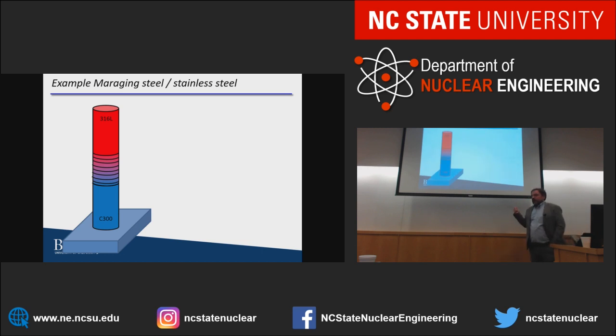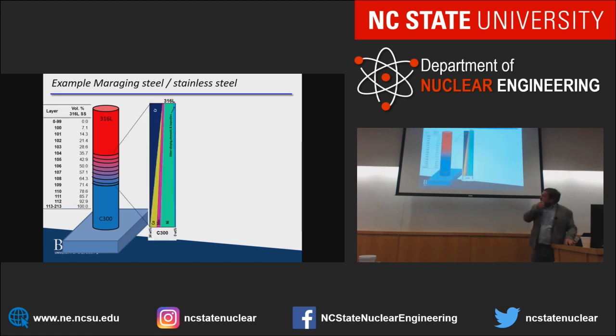316L is stainless steel. Maraging steel is an extremely high-strength material, typically used for tooling, wear-resistant components, valve balls, and anything that has friction involved, moving parts, right? 316L, on the other hand, is corrosion-resistant, non-magnetic, an austenitic stainless steel and much tougher, but lower strength than the maraging steel. So we're going to grade this layer by layer, starting on maraging steel and ending up with 316.